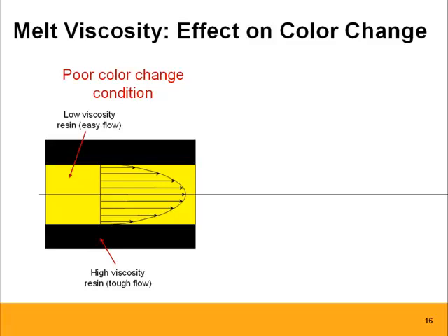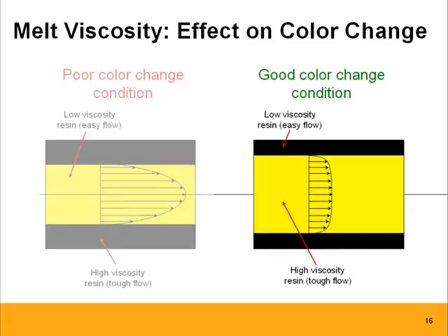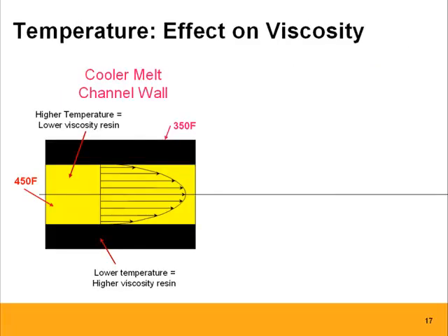A better situation, if you want to do quick color changes, is to have the high viscosity resin on the inside and really scraping those walls with the lower viscosity resin. Now, in many cases, of course, color change is done with exactly the same resin, so you don't really play that much with different melt flow indexes. But there's one way we can influence that too, and that is with temperature. Temperature has a significant impact on melt viscosity. So this is again the example that is not optimized for color change.